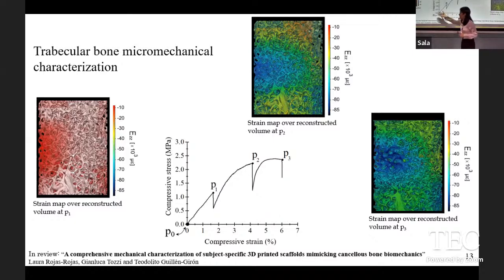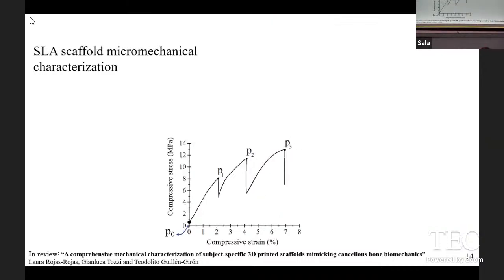So for instance, this image here shows the resulting strain map on the elastic section of the bone. For our bone, this is close to 10,000 microstrains, which is close to the yield point of bone, but the other sections don't show any strain yet. However, when we increased, as you can see, the strain map is focused in the middle section of the bone. We did the same study for the SLA scaffold.